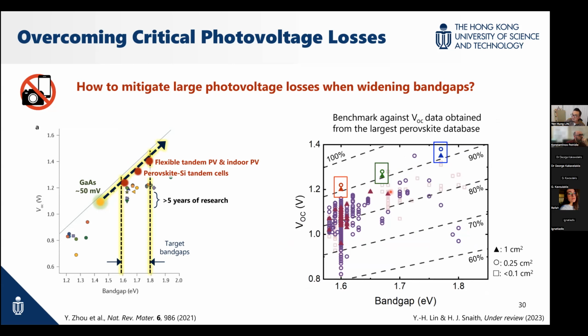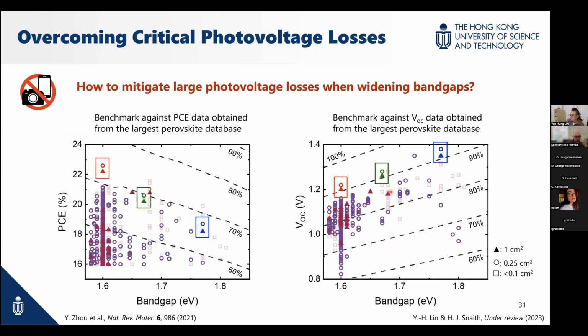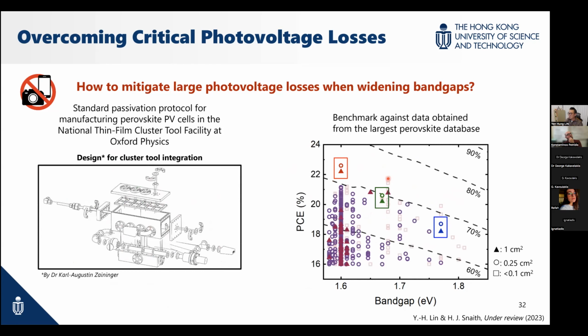This is just a benchmark against nearly over 1,000 data points, showing where we stand with this treatment to enhance the VOC above what is available in the literature, and also this is the PCE. One thing to note is we use different shapes to mark different pixel sizes, because when we increase the pixel size, normally we see a drop in performance, PCE and VOC as well. All right. This treatment is actually a non-solution process, done by vapor, and in my previous workplace they implemented this in a system designed as a tool that will be integrated into a fully evaporated system.